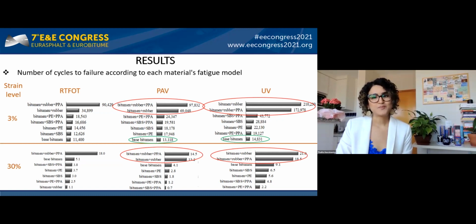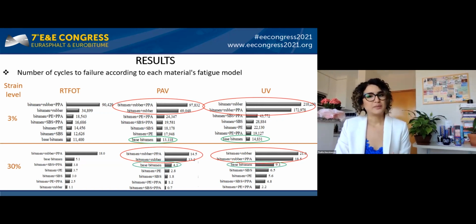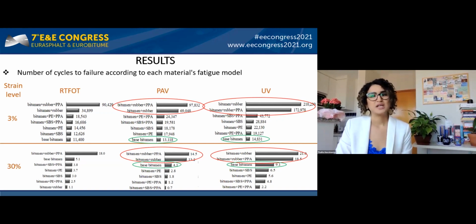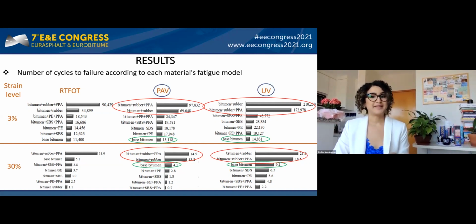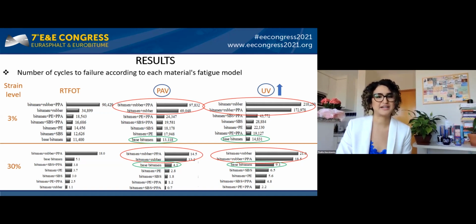The basic bitumen presented the lowest fatigue life at 3%, but it stands out well positioned at high strains in all aging conditions. The results show that bitumen modification is generally positive at low strains, but only some modifiers can increase fatigue life under high pavement strains. When we compare the PAV and UV aging, we can note that all materials' fatigue life for both strain levels was higher on the UV radiation, except for the bitumen plus polyethylene plus PPA at 3% strain level.